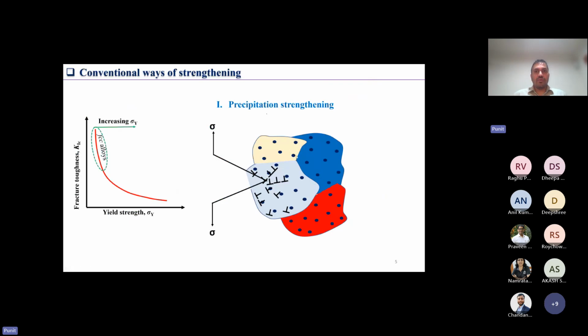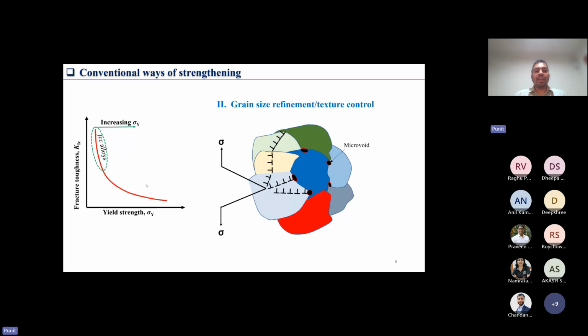But at the same time, what happens if you have a crack inside these materials, these precipitates would also block the movement of these dislocations. And because of that, you want to achieve this type of property improvement, but the actual trend would be that while you increase the yield strength, you will also see losses in the fracture resistance of the material. The second way we can do strengthening of FCC alloys is that